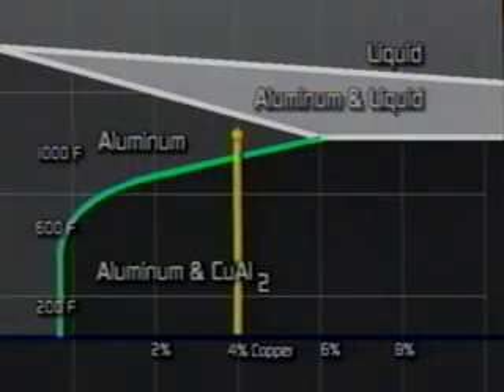Therefore, a heat treater heats this work-hardened material to a temperature at which all the copper atoms are in solid solution, and then quenches. This helps retain the copper atoms in solid solution even though the alloy is no longer hot.